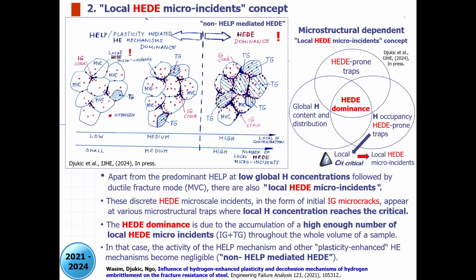So here is the microincident concept, proposed in 2021 with a group of researchers from Australia and Serbia, which tells us that even at a low critical hydrogen concentration, we have localized decohesion phenomena on the microscopic level. It's the so-called HEDE microincident concept. And in the case of activity of the HELP mechanism and other plasticity mechanisms, we have so-called non-HELP-mediated HEDE, which means that we have a full predominance of the decohesion mechanism after accumulation of large enough local micro HEDE incidence. In that case, we have HEDE dominance. So we have both plasticity-mediated fracture and also local intergranular and transgranular brittle failure due to the HEDE mechanism. So they operate simultaneously.